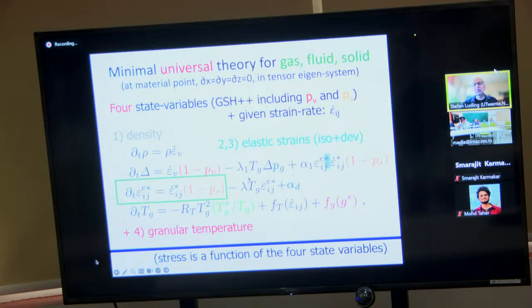Okay, but if you want to go faster, if you want to include rate dependence into the theory, then you also need an evolution equation for this relaxation rate. Okay, and that is the classical one. And then you have something which depends on the strain rate itself, and you have something which depends on the yield, referring to my previous speaker: how close are you to the yield of the material? And that also influences the so-called granular temperature, the relaxation rates.